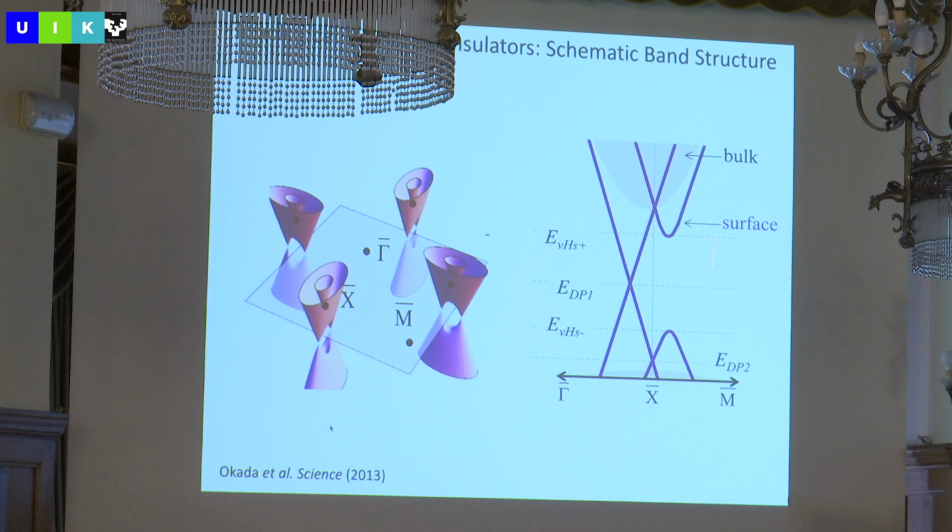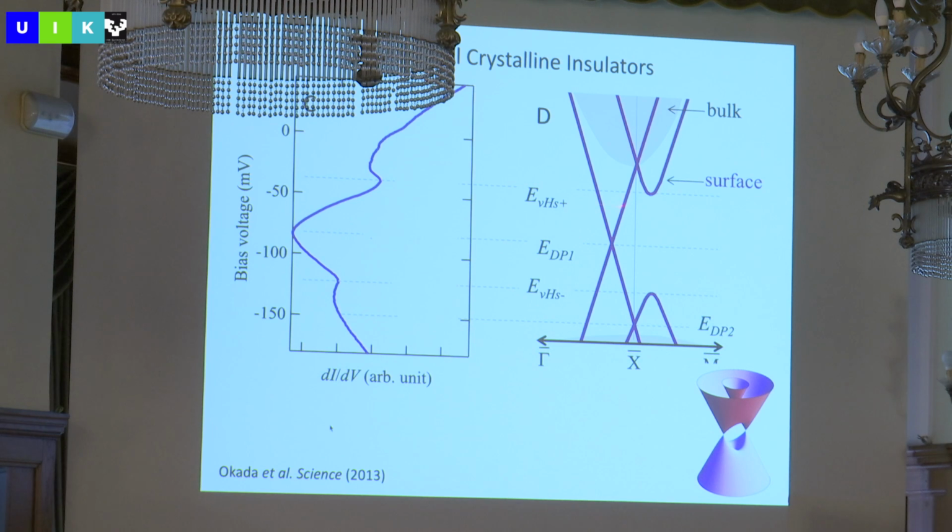this is the dispersion of the system. This is what the band structure looks like. So you have this linear dispersion right around the Dirac point, and that's what gives you that V shape. And then those little coherent peak-like objects are coming from this flat portion right here, which is known as a Van Hove singularity. So basically comparing this to this flat portion of the surface state, this Van Hove singularity gives you the sharp peak in the density of states. And then this linear dispersion, in 2 dimensions, you get a linear density of states in 2D, okay?